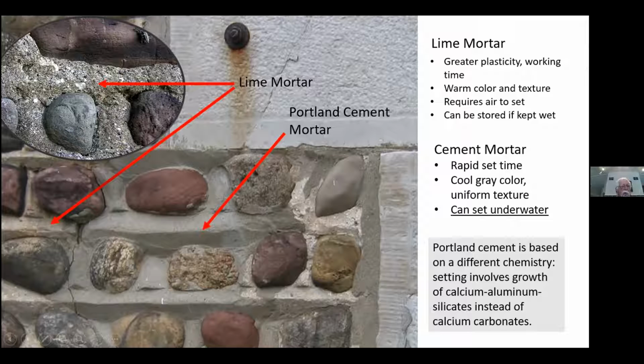And a typical lime mortar has in it, you can see these white spots here and up here and over through here. Those are chunks of lime that didn't completely go into the putty state. So those are bits of quicklime which then get translated into the mortar. But that tends to give the mortar a nice warm color and texture. Now, you can contrast that with our modern Portland cement mortars. In this wall, there was a Portland cement repair, and this gray colored material that has this dull gray color that you see down through here, that's all Portland cement mortar.